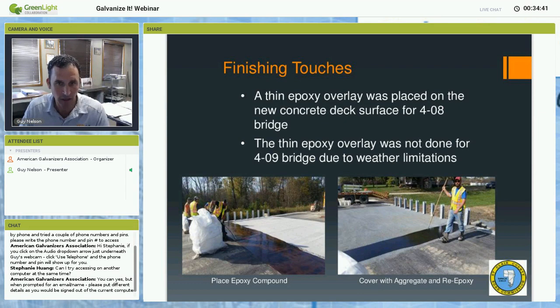precast deck panels, and epoxy and grouted joints and the deck joints between the elements. Unfortunately, on 409, due to weather limitations, they were not able to put the epoxy overlay on. We were out there at the beginning of this year and found that the deck without an epoxy overlay has performed great. They still plan on doing it sometime this year, but so far the deck joints and grout pockets are performing very well, and we don't see any cracking.